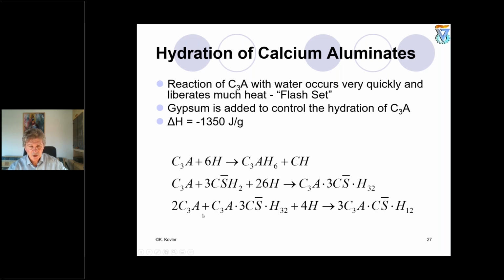And then when gypsum is ending, the C3A, which is still a part of Portland cement, starts reacting with this ettringite. And these two products are, how to say, eating each other. And then we have a relatively quiet mineral, not making any problems, which is called monosulfate. Monosulfate because you see only one part of calcium sulfate here, in contrast to three parts of calcium sulfate in the ettringite formula, with only 12 molecules of water chemically bound. So these three reactions are extremely important to illustrate the need to retard Portland cement with gypsum.